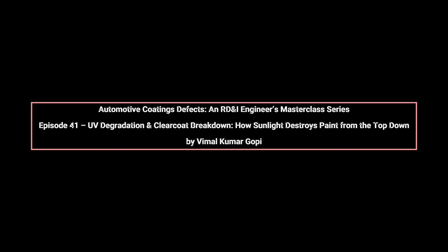Microcracking forms, allowing moisture and contaminants to penetrate deeper. Chalking occurs as pigment or filler particles are released from the polymer matrix. At this stage, gloss loss accelerates, and repainting becomes the only effective repair.